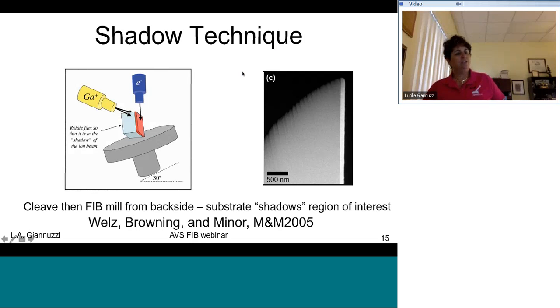Shadow technique is another method. So this group basically just used the sample itself. They just used the substrate itself as basically a mask to FIB mill a thin section. So it's hard to see what's going on here, but the idea was to FIB mill from the back side of the substrate, leaving behind a thin section so that the thin layer here was not touched by the FIB.